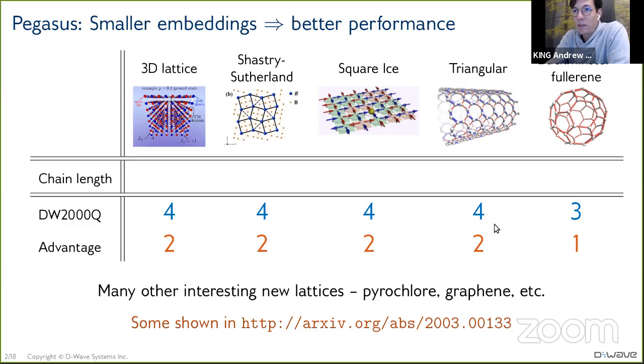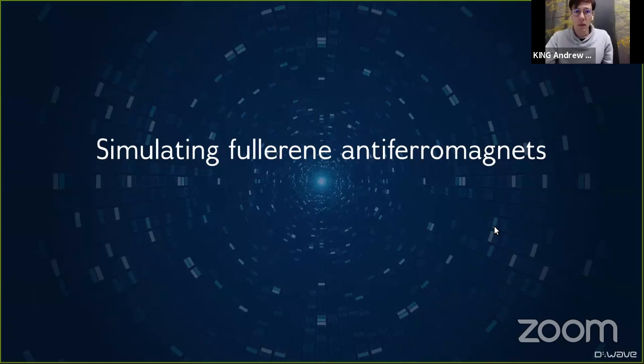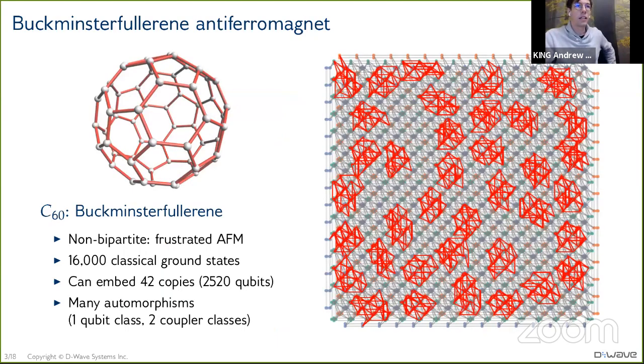But in the Advantage processor, you can embed it without using chains at all. So I'll use this Buckminster-Fullerene as a nice example of important things that I want to communicate with people who want to do simulation of systems in the D-Wave processor. The nice thing about having a non-bipartite graph is that you can put +1 on all these couplers, and because you have odd cycles, you have frustration. This is a Buckminster-Fullerene or soccer ball graph, and all the cycles here have length 6 or 5. One of the nice things about this graph is that it has tons and tons of automorphisms, and we're going to exploit those automorphisms. I'll separate the couplers by class: the blue ones are between two 6 cycles, and the red ones are between a 5 cycle and a 6 cycle.